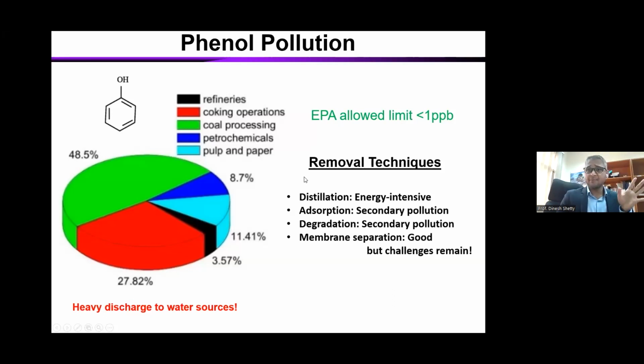There are removal techniques existing for phenol removal. You are not the only one doing it. The well-known techniques are distillation, adsorption, degradation, and membrane separation. Each technique has its own merits, pros and cons. In the case of distillation, it's a good technique, but the issue is you need energy. You need to heat it up, so it's an energy-intensive system. The problem with adsorption is that sometimes the adsorbing material itself can cause secondary pollution to the water. That is the headache. Degradation is the same, because the degraded product can be even more toxic than the original pollutant.